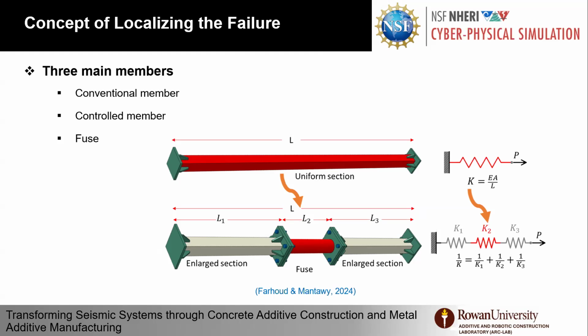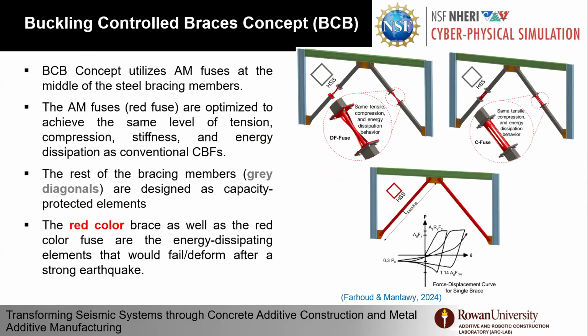And we went through topology optimization and structural optimization processes to size the fuse so that we achieve the same energy dissipation, tension and compression, and system stiffness as the original concentric brace frame. And as you can see here on the right side, I'm showing the stiffness for both one brace and what we call hybrid brace. So in a system, on the lower side of the right figure, you can see that one brace alone dissipates in this manner as a yield in tension, then buckle in compression. The brace itself as a system is symmetric because every brace changes between tension and compression depending on the direction of the ground motion. However, the top 2 options that we have here, we have a two design.